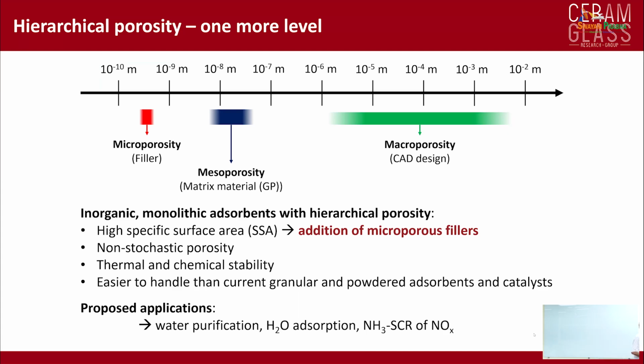So we can exploit the macroporosity by CAD design. We can exploit the mesoporosity by playing with the composition of the geopolymer and different other features. But we would like also to have additional specific surface area and behavior. So one thing that you can do is add some fillers that have microporosity. Such fillers could be active carbon, which is very stable inside the geopolymer, or could be zeolites. Not all zeolites are chemically stable inside a geopolymer because of the high alkalinity, but a wide range of zeolites are. So we started adding microporous fillers in order to further enhance and modify the behavior of the material.